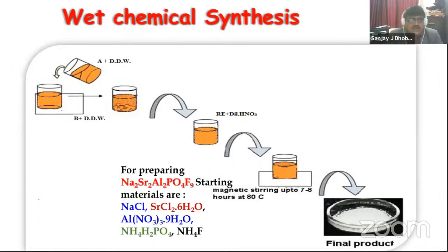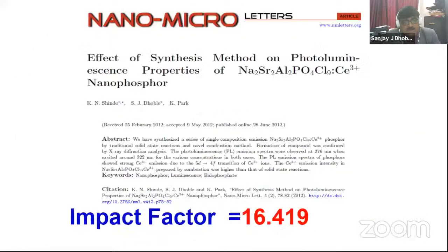You can see here that the materials in the stoichiometric ratio are dissolved in double distilled water, and if there is any other impurity you can add it, and then it is heated critically from 60 to 80 degrees centigrade at a particular rate, and then the material is prepared. In my laboratory, this is the Na2Sr2Al2PO4F9. This is a very complicated compound, also prepared by this method, and the result of this material is published with a high impact factor.